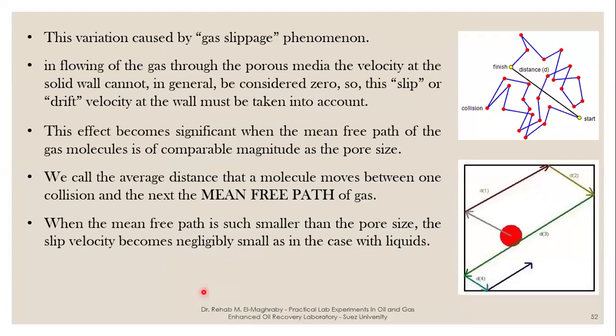This is because of the gas slippage effect. Normally, when you have liquid flowing in a tube, the liquid near the tube wall will have zero velocity. But in the case of gas, the gas near the tube wall does not have zero velocity. It has a velocity, which is called the gas slippage effect or phenomenon. So we find that as you increase the pressure, you can overcome this phenomenon.